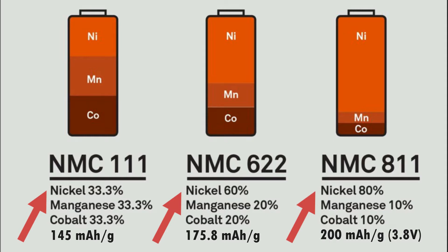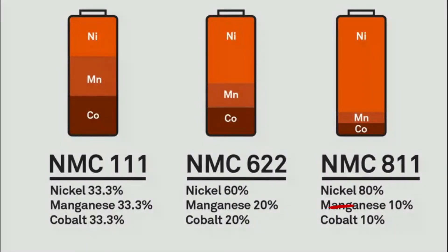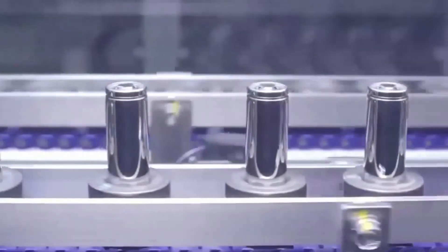And more so, it is relatively affordable. The main argument for NMC811 is that it needs less cobalt — about 10%, down from 20% in NMC622 or approximately 33% in the NMC111. That means big savings because cobalt is a very expensive component with a very questionable supply chain. Cathode materials account for about a quarter of the cell cost, and a reduction in cathode material cost spells a significant reduction in the overall cost of the battery.